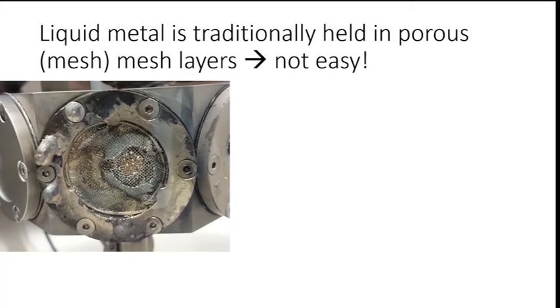So like a sponge, the liquid is sucked up and it stays in place quite nicely. And one typical way to make these porous structures is to use meshes, so basically layers of woven metal wire. But this is not straightforward. So here you see a sample that we exposed in Magnum at the beginning of my PhD, and after a single plasma exposure, we melted through all these mesh layers, and it's a complete wreck, so to say.